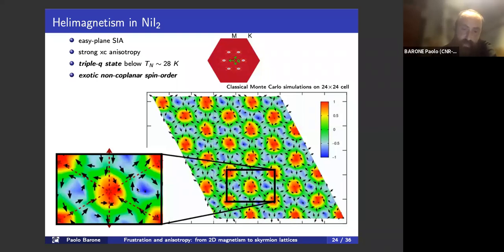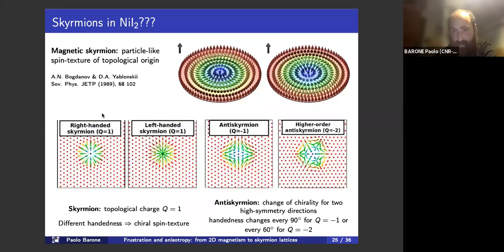Even more interesting, we see that the in-plane component of the spin texture is very unusual. And actually, one can identify these 3 axes around which the handedness of the in-plane component changes sign. And now, thanks to the previous speaker, we know that this suggests that we have skyrmions in the system. So we have seen that there are a lot of different types of skyrmions.